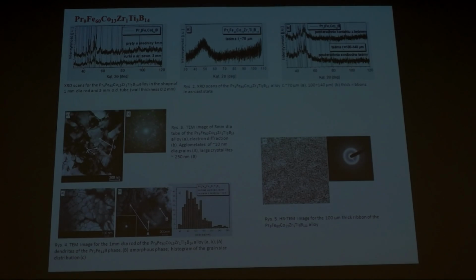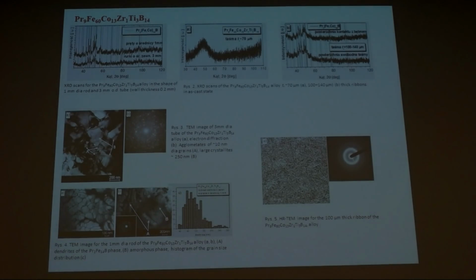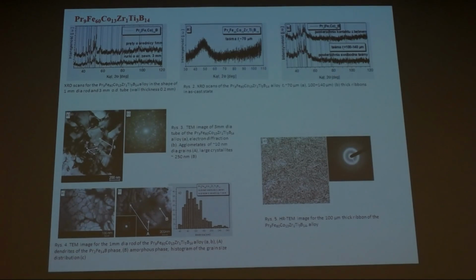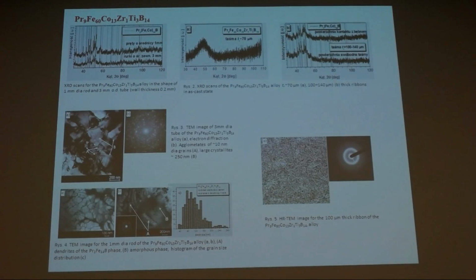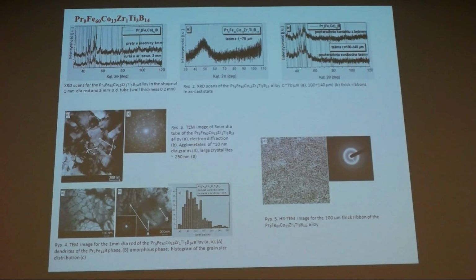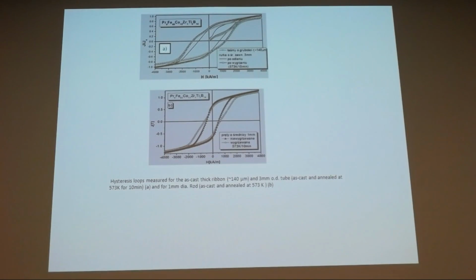The other alloy, we have moved to some alloys with a higher amount of rare earth, 9 atomic percent, and we were able to cast directly a nanocrystalline structure in the form of rods and tubes, and also for very thick ribbons it was possible to cast partly crystalline, nanocrystalline material, which reveals quite high coercivities, roughly more than 1,000 kiloamps per meter for the thick ribbons and tube samples, while for the rod samples it was a rather moderate coercivity.